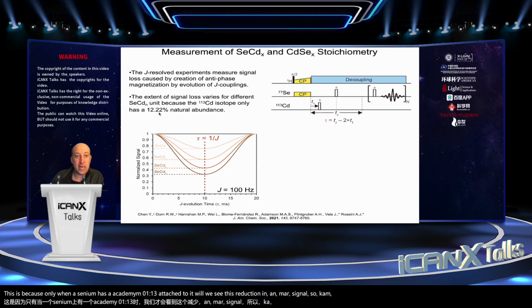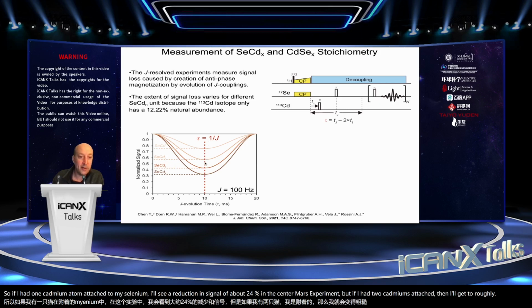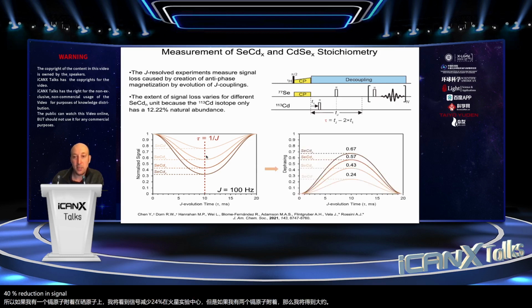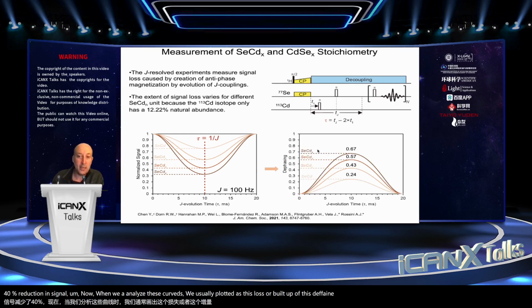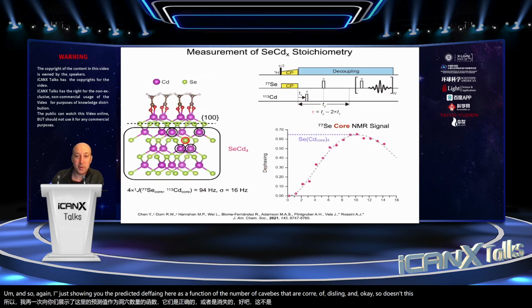So cadmium-113 has an abundance of about 12%. If I had 1 cadmium atom attached to my selenium, I'll see a reduction in signal of about 24% in this NMR experiment. But if I had 2 cadmiums attached, then I'll get to roughly a 40% reduction in signal. When we analyze these curves, we usually plot it as this loss or buildup of dephasing. And so again, I'm just showing you the predicted dephasing here as a function of the number of cadmiums that are correlated to selenium. Okay, so does this experiment work?